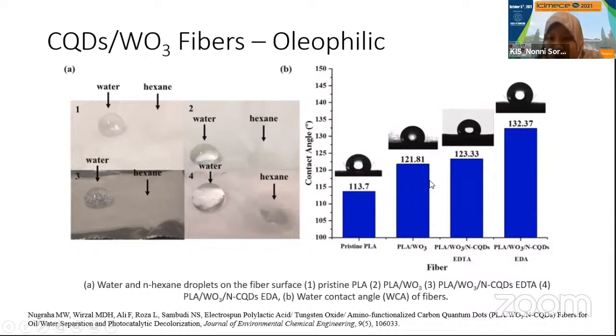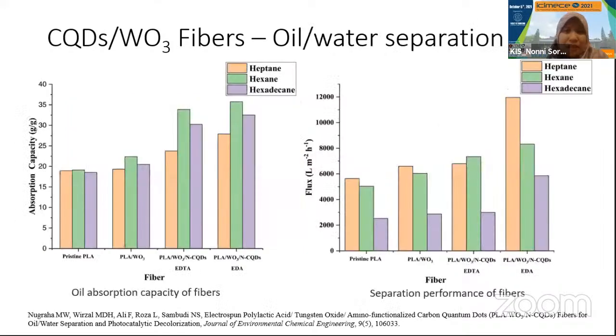Okay. So based on the spinning results, the contact angle of the polymer itself is increasing, right? It can reach around 130 degrees when we incorporate this material into the polymer fiber. The increase of the contact angle makes the fiber mats become hydrophobic and oleophilic. So it absorbs the oil, but it rejects the water. Okay, so we try to separate the heptane, hexane, and hexadecane from the water mixture.